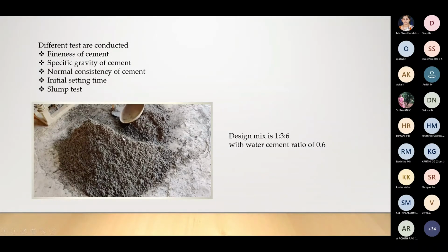Then mixing has to be done, right? Before that, they have taken fine aggregates and coarse aggregate. For that, different tests have to be conducted. For cement, it may be the fineness, specific gravity, normal consistency, initial setting time, slump test; all tests have to be conducted. Then they have mixed cement, sand, and coarse aggregate. The design mix is 1:3:6, with a water cement ratio of 0.6.